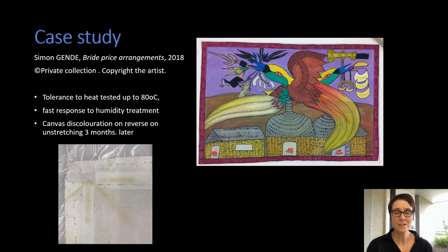The binder of this painting was not able to be determined using FTIR-ATR, possibly because of its low content, and the priming was found to be pigmented predominantly with chalk. The canvas is on a plain weave cotton. During stretching at QAGOMA, heat tolerance was tested, and again no visible effect on the priming was noted at 80 degrees Celsius.